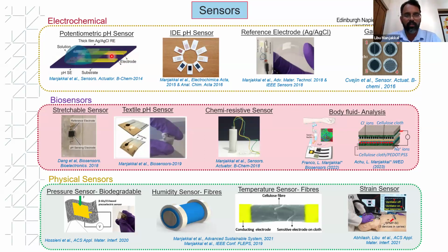In electrochemical pH sensing, one of the major problems is to fabricate a stable, fully solid reference electrode, and I overcame this by developing a new silver chloride paste integrated with a glass composite powder. You can see from here that this is a potentiometric pH sensor. Another type of sensor we fabricated during that time is an interdigitated sensor, where if the reference electrode has some issues, or for an impedance-based or capacitance-based measurement, we used an IDE-based pH sensor.